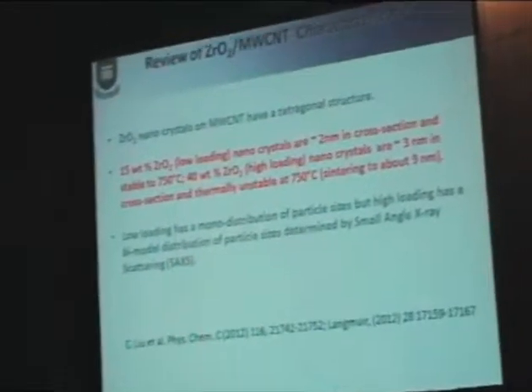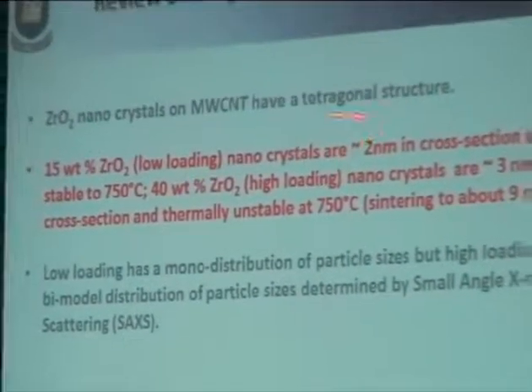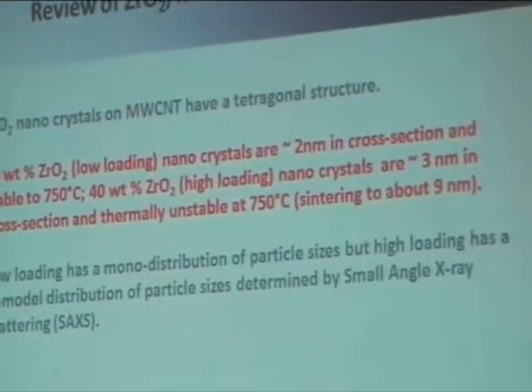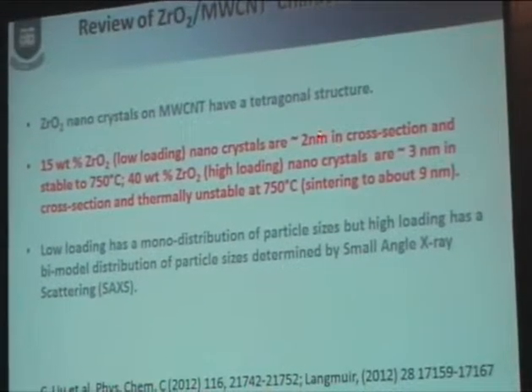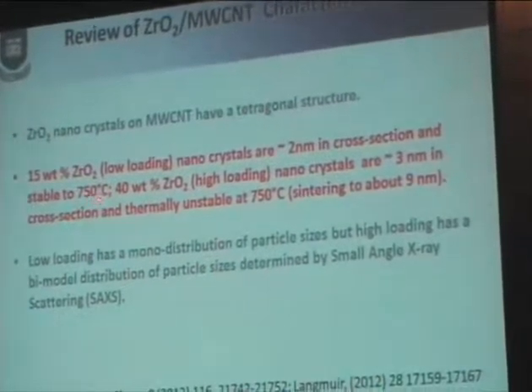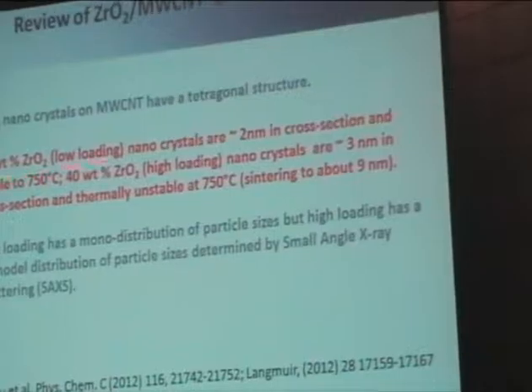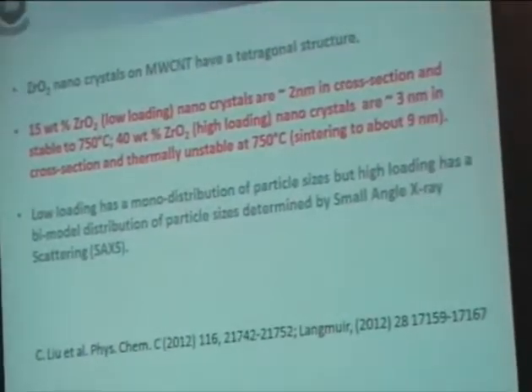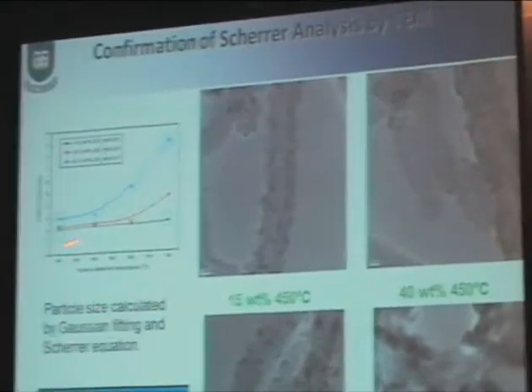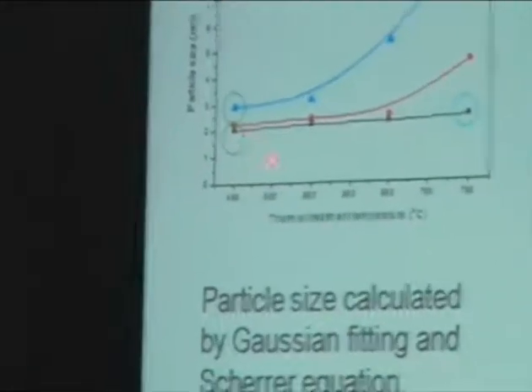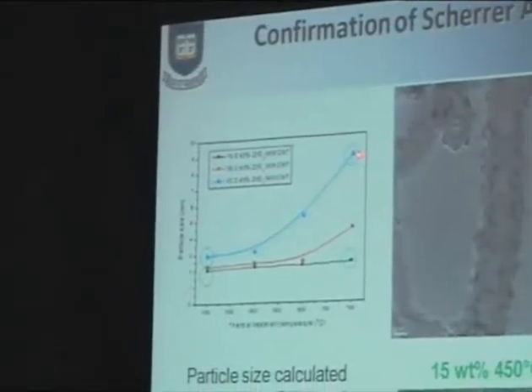The next thing I want to say is that we are going to focus our attention on weight loadings around 15%, because only in that range do we have thermally stable small particles in the range of 2 nanometers. That means stable up to about 750. Higher loadings, you get larger particles initially, and they are unstable towards thermal sintering. Here we're going to look at them by Scherrer analysis with X-ray diffraction. This is too small for you to truly read, but with 15% weight loading, they start out at 2 nanometers, and after being heated to 750, they remain that. At about 40-some weight percent, they're more like 3 nanometers, and after 750, they're up to about 10 nanometers.